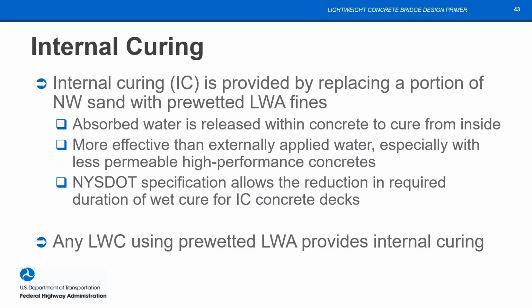Internal curing is discussed slightly. It's something that FHWA now has in their Every Day Counts 7 program, labeled as EPIC 2. With internal curing, you take some fraction of the sand out of a conventional mixture and replace it with pre-wetted lightweight aggregate, and then that pre-wetted lightweight aggregate provides the internal curing and does have a significant improvement to the properties, even though it's only a fraction of the sand that's being replaced.